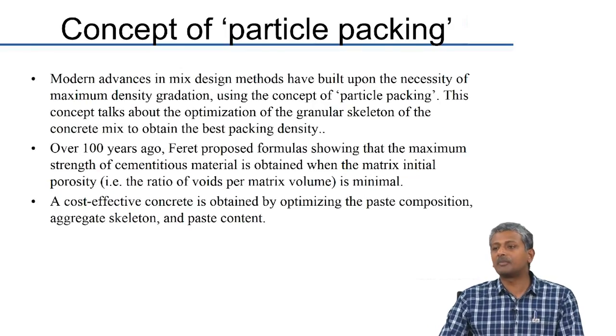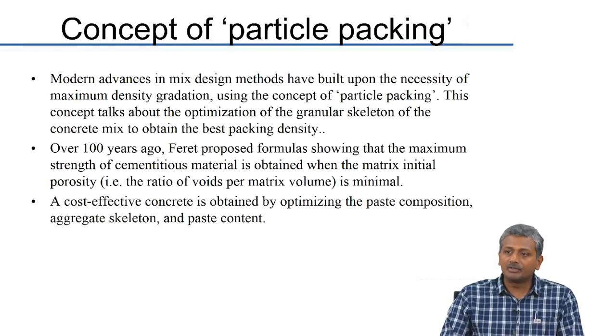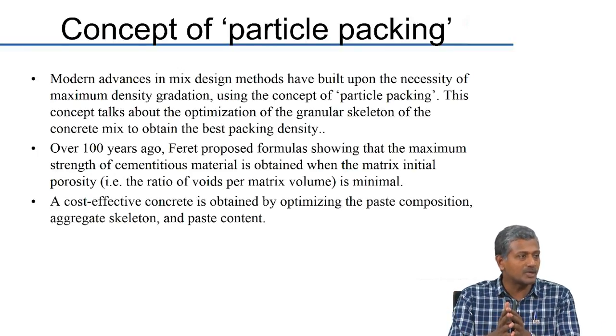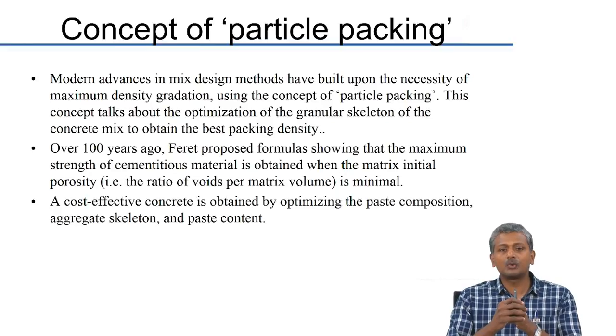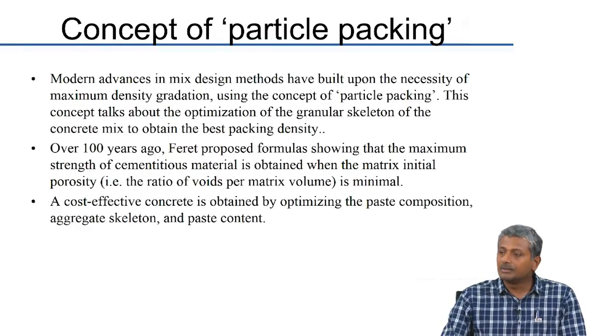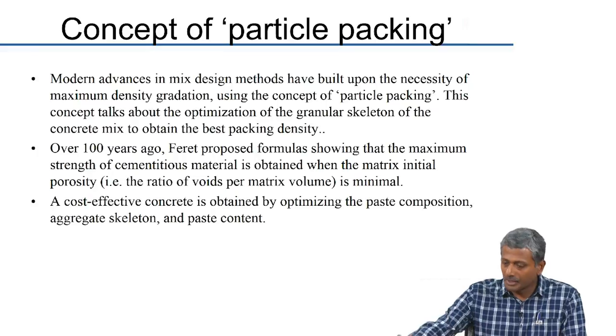The gradation gives you a range — if your curve falls within that range, you satisfy that particular gradation requirement. This is based on Fuller's formula, also called the 0.45 power gradation, which was adopted by several highway agencies and public works departments worldwide. This 0.45 power rule has been followed largely everywhere until the recent past. Now people have started realizing that this rule probably does not support modern concretes where we are increasingly using very fine constituents such as mineral admixtures, which can contribute filler effects.